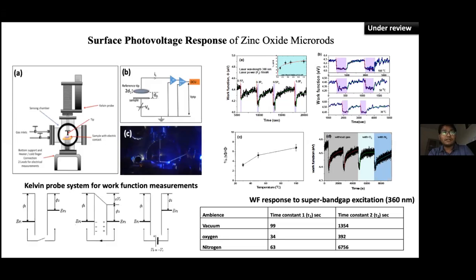So the faint blue is 100% oxygen. This is somewhat 20% oxygen, the ambient, and this is nearly 0% oxygen. You can see that the current or the work function takes a very long time to recover when there is absolutely no oxygen in the atmosphere. That means when there is oxygen in the atmosphere, once these photo carriers are generated, some of them are trapped by these oxygens. This helps in the recovery of the photosensor. So that is why the atmosphere is basically tuning the response function of your photosensor device.